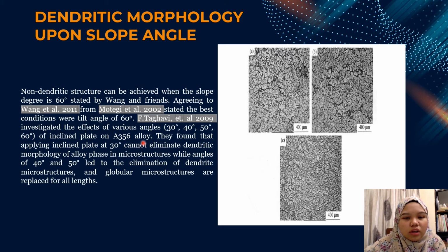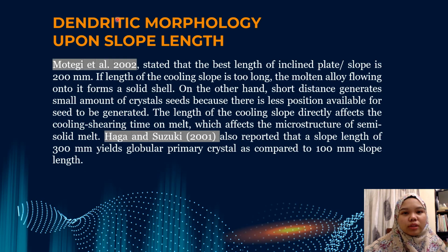A356 alloy. They found that applying an inclined plate at 30 degrees cannot eliminate the dendritic morphology of the alloy phase in microstructures, while angles of 40 and 50 led to the elimination of dendrite microstructures, and globular microstructures replaced them for all lengths. For dendritic morphology upon slope lengths, Motegi et al. 2002 stated that the best length of inclined plate or slope is 200 mm.